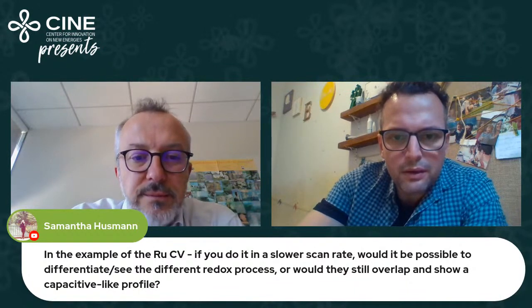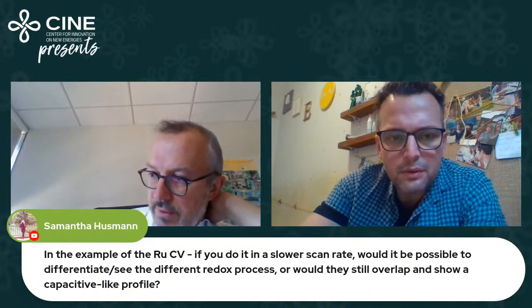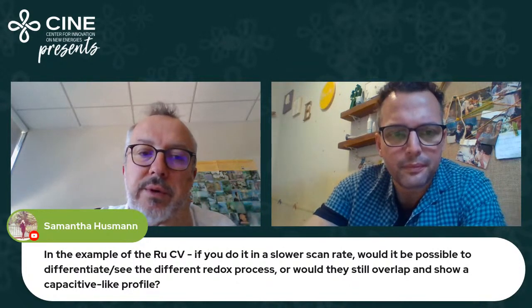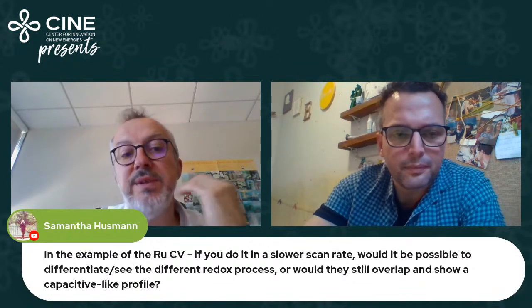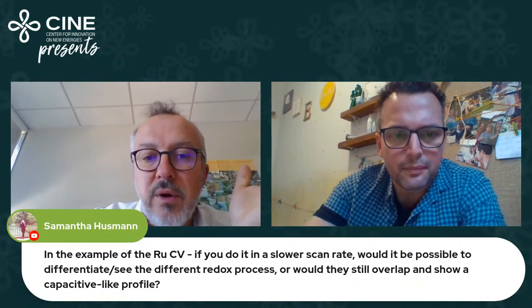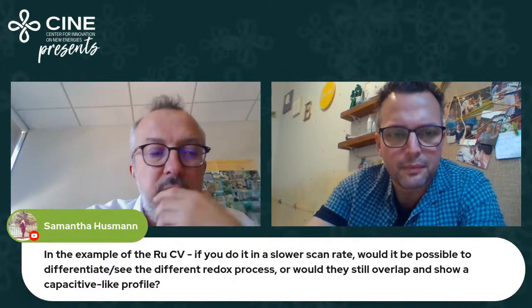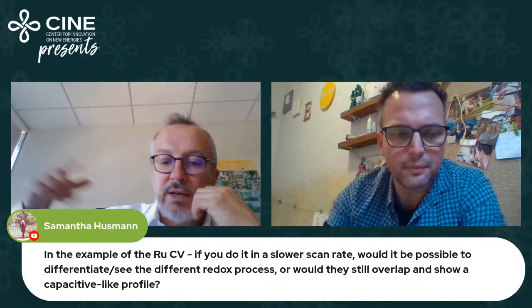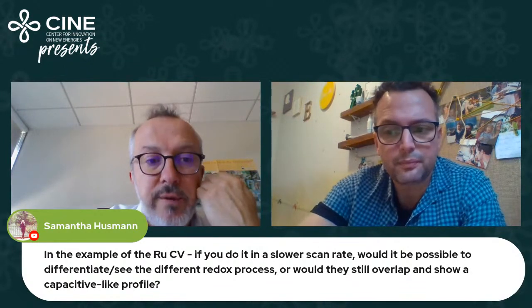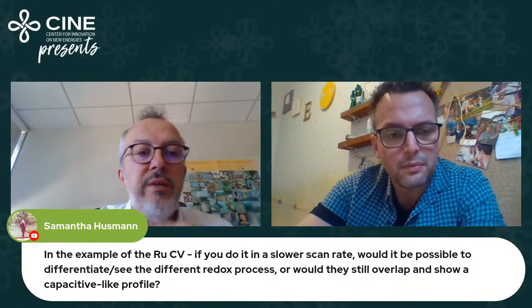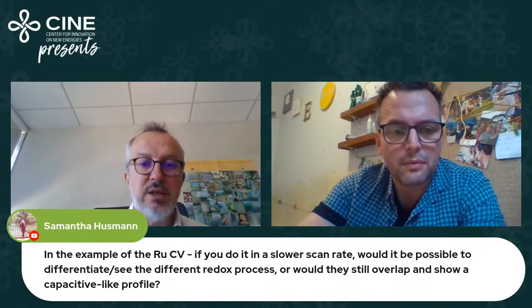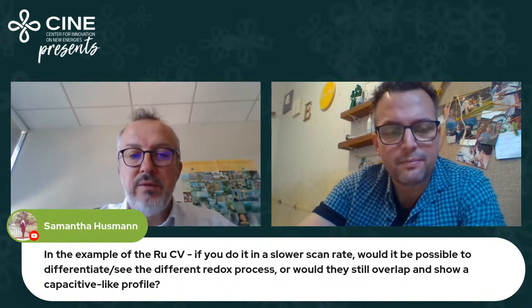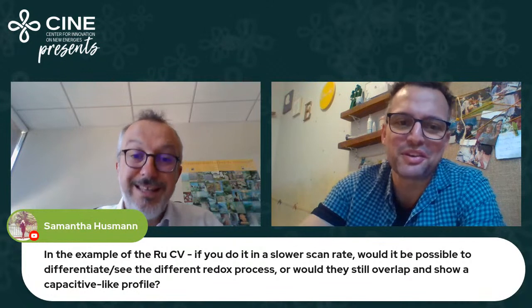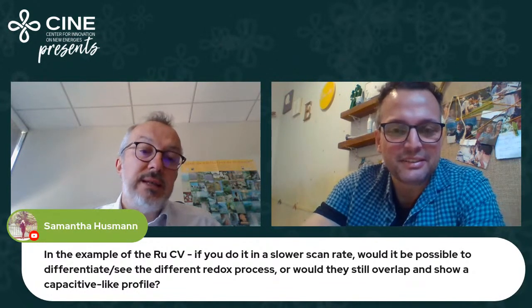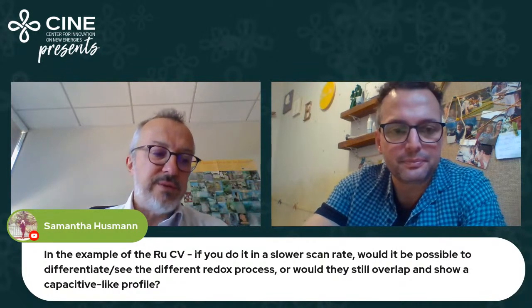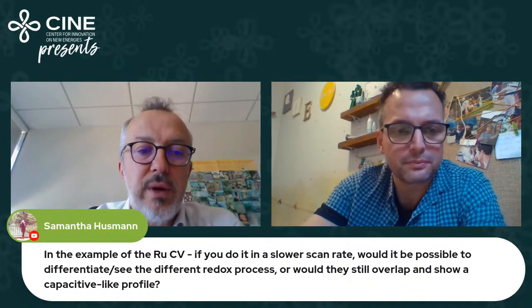If you go to a very slow scan rate, you favor the diffusion-limited process versus the capacitive behavior. So yes, you're right in a way, but there is a limitation. This limitation is more or less the leakage currents of the parasitic redox reactions, which are linked with, for instance, electrolyte oxidation at the extreme parts of a CV. So yes, decreasing the potential scan rate is a way to favor diffusion-limited reactions versus capacitive reactions. But again, it's quite difficult, even at very slow scan rate, to differentiate the contributions. And you lose the power, so you want to increase the power. You can use the Trasatti method, because Professor Trasatti, who passed away a couple of months ago, designed a very nice method to extrapolate to very low or very high scan rate.